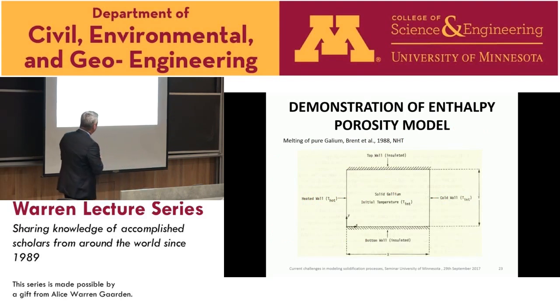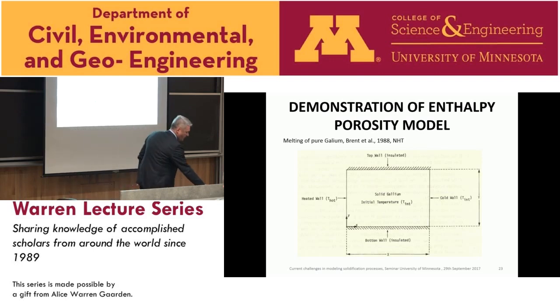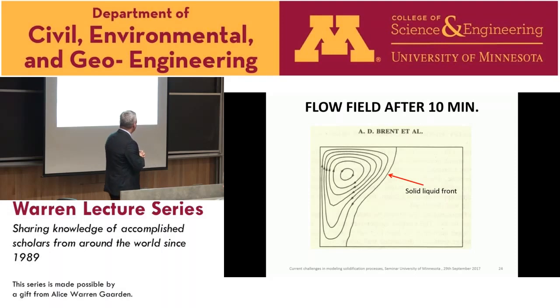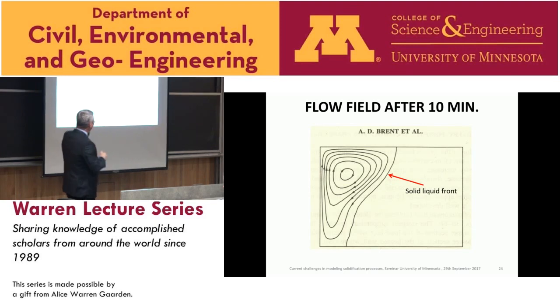A demonstration of how the enthalpy porosity model works can be found in the paper on melting of pure gallium from 1988, the original paper of Brent, when they tried to see what happens with two insulated walls and two walls between the cold and heated wall, and then you have a melting of gallium. And you can see that the solidification front looks like this. If you assume the absence of movement, you will have a flat line moving from left to right. Because of flow, you have a deviation of the solid-liquid front.